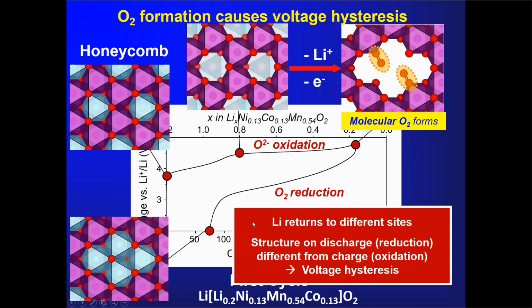But what you see here is that if you create a small vacancy cluster, even one with just 3 vacancies, allowing the formation of molecular oxygen, you reduce the energy of the system really quite considerably. And this is mainly driven by that covalent bond formation. And then this shows you that if you just have 1 more vacancy, you now have 2 molecular oxygens. And of course, this pushes the energy down even further. So you get a big step here and a slightly smaller step here. But the point is that by allowing these small vacancy clusters to form, you can accommodate the molecular oxygen in the structure, and it is a thermodynamically attractive process to do so. Of course, you have to move metal ions to do it and create these kind of environments, and that's the other part of this, which I'll mention in a few moments.